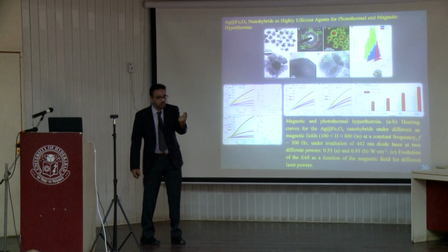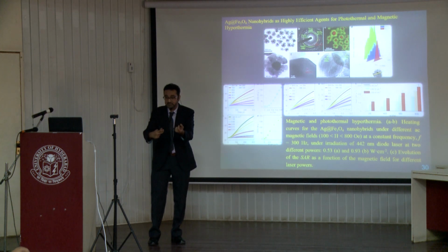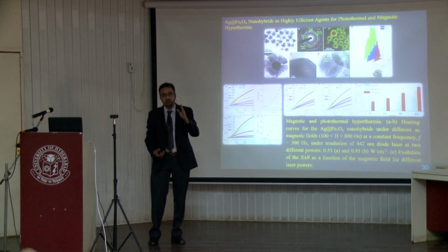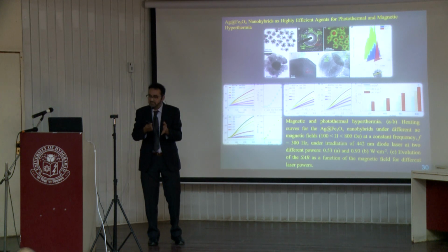You can actually have a gold nanoparticle, because it's polyhedral, nucleate the growth of iron oxide which attaches to it in the form of petals. You can make these small nano flowers. And the reason is, if you look at the lattice constants of gold and magnetite, they differ by just a factor of 2. So you can have epitaxial surfaces.